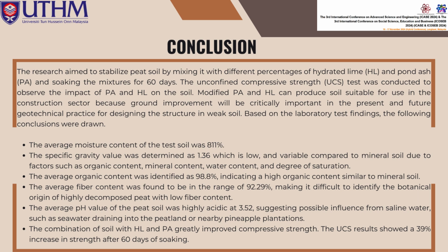The soil's pH was 3.52, indicating high acidity, possibly from saline water or nearby plantations, and combining hydrated lime and pond ash significantly improved compressive strength, with a 39% increase after 60 days.